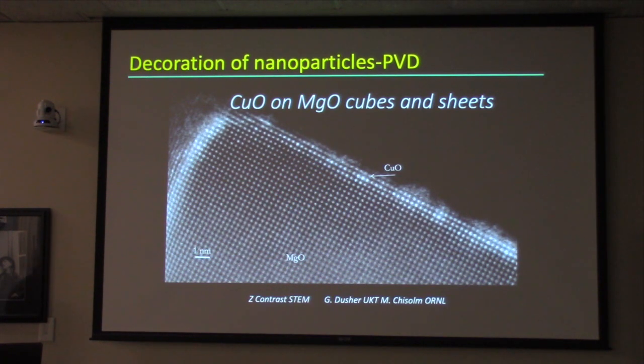Now it's not ordered. It actually turns out to be a little bit stochastic. The fact is, what you can actually see if you look at the normal position is that the copper is randomly distributed in that region. And so we're really excited to take a look at the chemical properties of this. This is a new experiment, and Matt Chisholm and Gert Duscher have been kind enough to let us sneak into places where we would normally have to pay to use them.